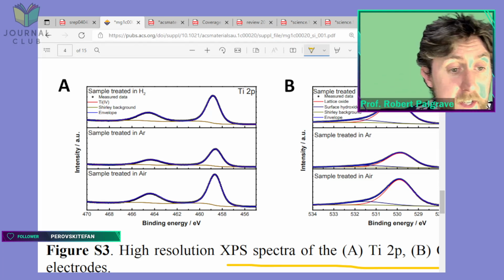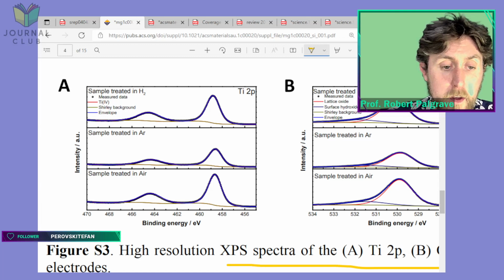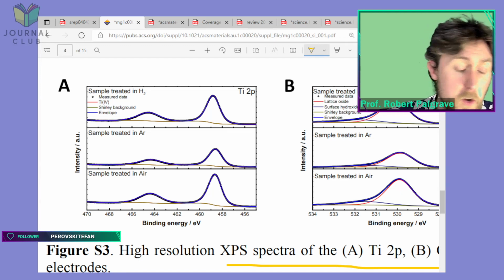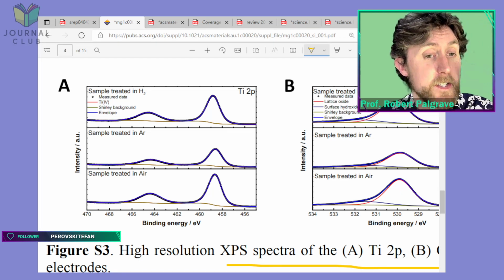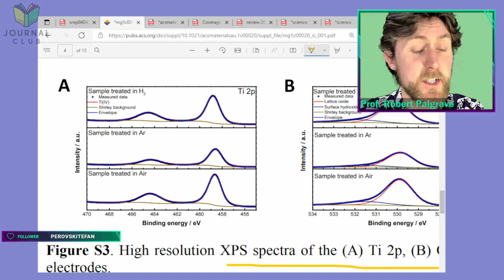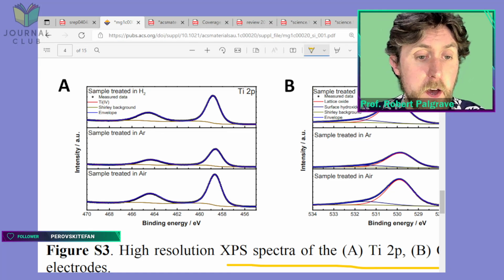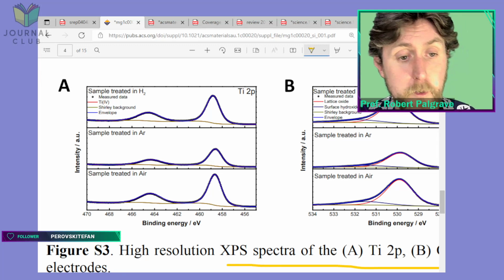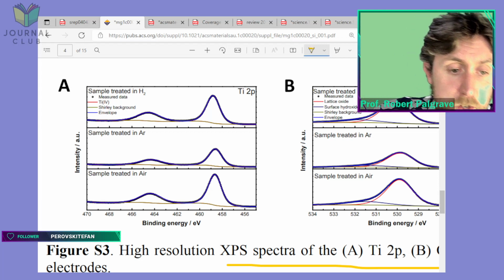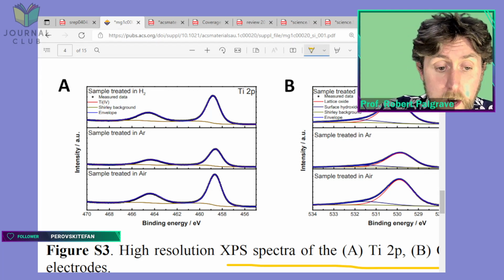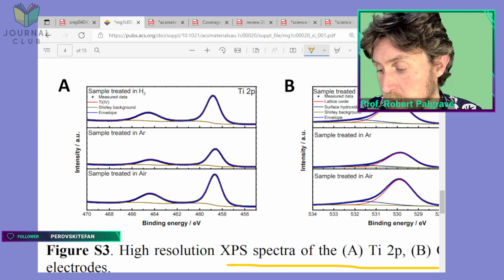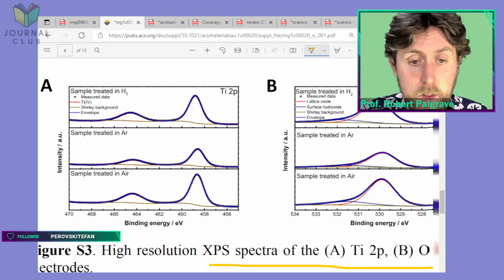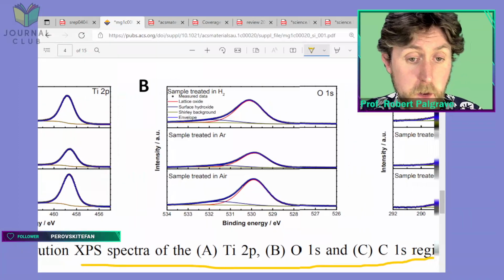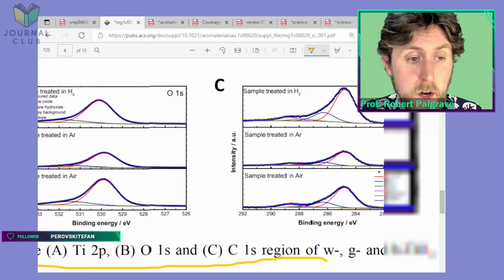But the main point is that they don't see a big extra peak in the black TiO2, so the top one, which would correspond to titanium 3+. If you had a mixture of titanium 3+ and 4+, you'd expect to see another environment for the titanium, another peak down here for the 3+ environment. But you don't see that, or at least they're not showing it. It's not very obvious here. So that's kind of interesting, for the reasons they described earlier: one of the hypotheses is that you make Ti2O3, titanium 3+, on the surface, but you're not detecting it.